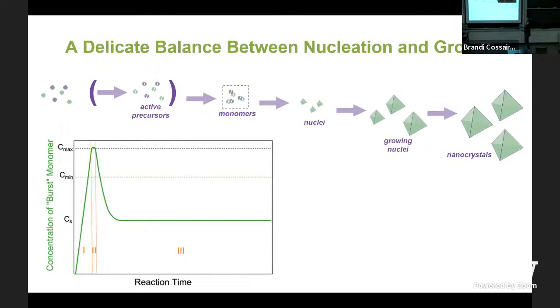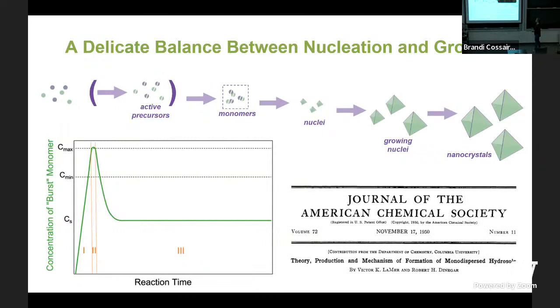And this description of the formation of size uniform nanocrystals was actually first developed by LaMer and Dinegar in 1950. So what they described in this seminal paper is that you can control the monodispersity of your nanocrystals, of your colloids, through this burst nucleation mechanism. So what we're plotting here on the y-axis is the concentration of these monomers over time. And what we find is that if we can control the formation of these monomers, they're going to build up in concentration until you reach some critical concentration, at which point nucleation is going to happen. And then you're going to drop below that critical concentration, and you're going to grow slowly from the remaining monomers